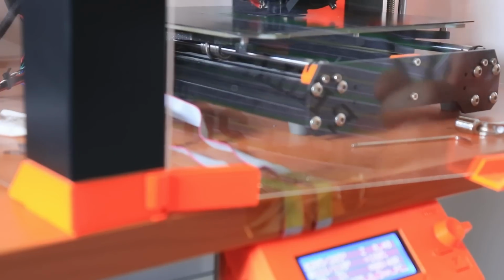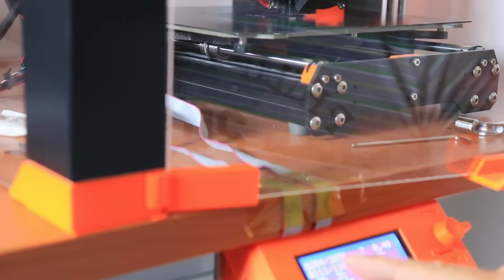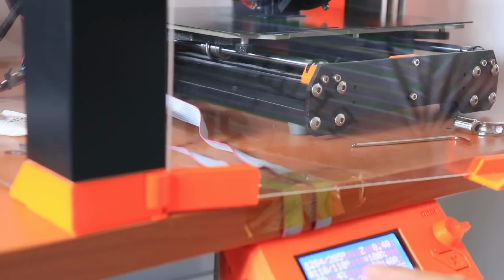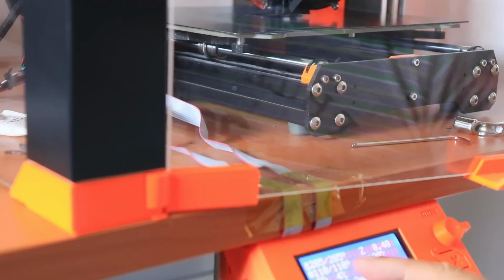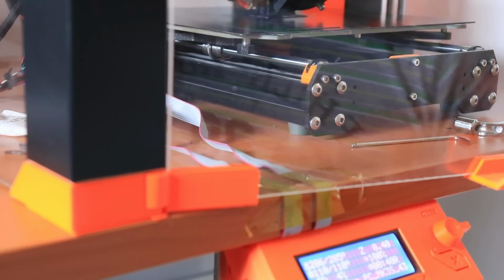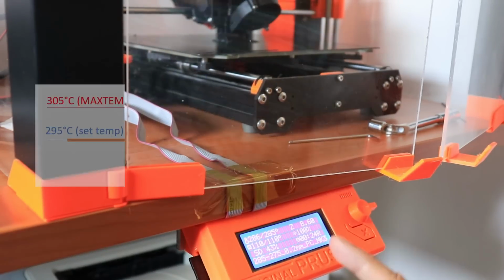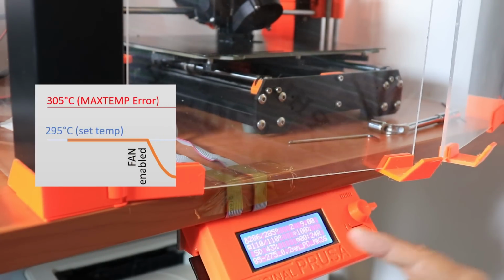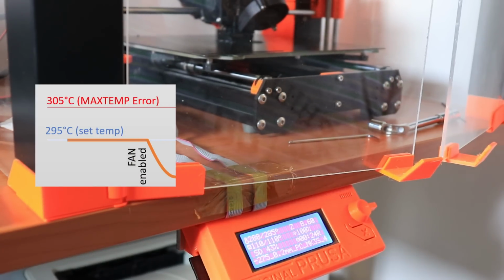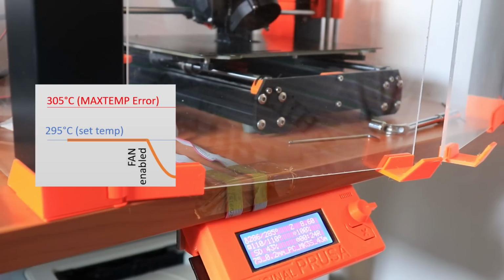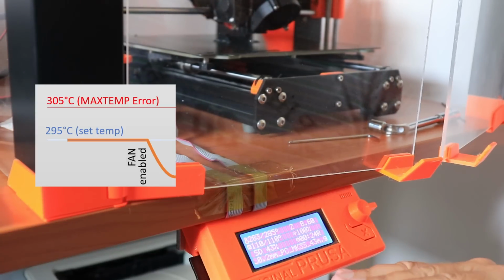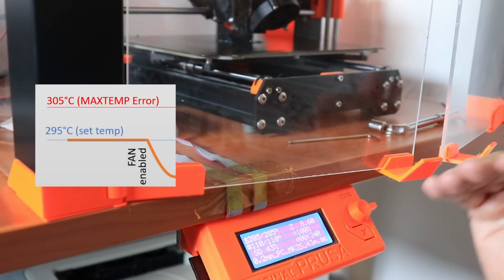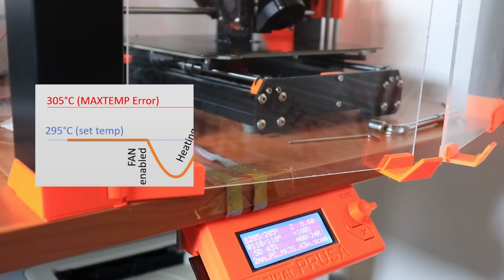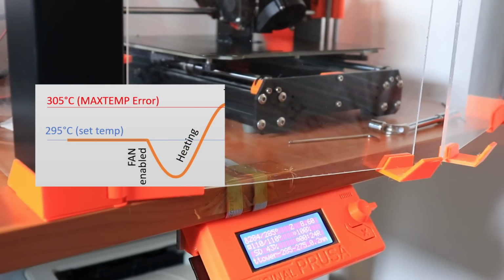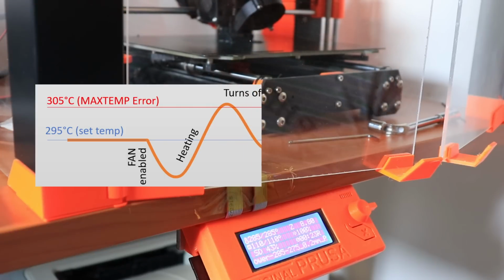I restarted the printing of the temperature tower, but now from 285 degrees Celsius, and the bed temperature I reduced from 115 to 110 degrees Celsius. Now I know what happened. On this height it starts with the fan very minimally, 20%, but that's the settings in the Prusa slicer. And on 295 it cooled down and it starts with the heating and probably shoots over that limit, and then I got the max temperature.